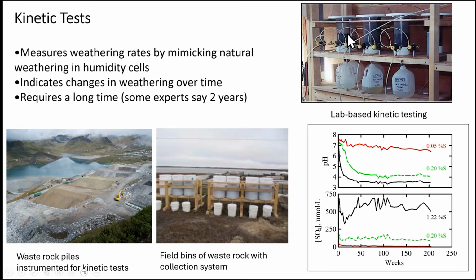This is very typical. You have about 1 kilogram or so of crushed material, whether it's potential waste rock, they still crush it quite fine, or tailings, and they create rain, so water is run through for 3 days, and then they dry for 3 days, and they test on the 7th day. That's typically the way they do it. So you can see the fluid being gathered here. And these are run for a long time. Many decision makers think you need 2 years of data. So you can see how challenging this is for a company that's trying to bring something into production.